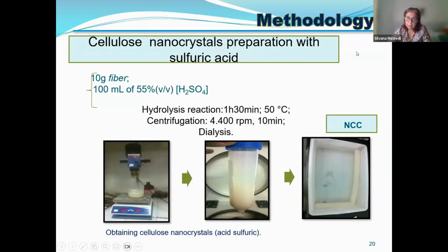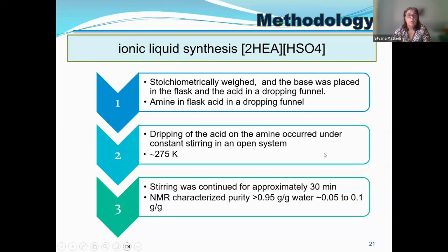We prepared the nanocrystals with sulfuric acid. That's basically hydrolysis, centrifugation, and then dialysis. This material for the composites we named NCC. Or we synthesize the ionic liquids. We normally synthesize them in the lab. For the bmim, we bought it from Sigma Aldrich, but the ammonium, the protic ionic liquids, we normally make at the lab.